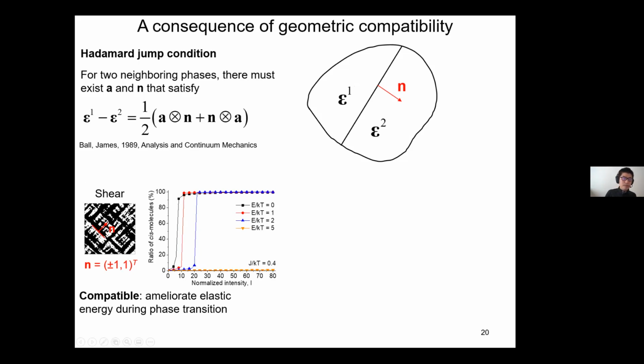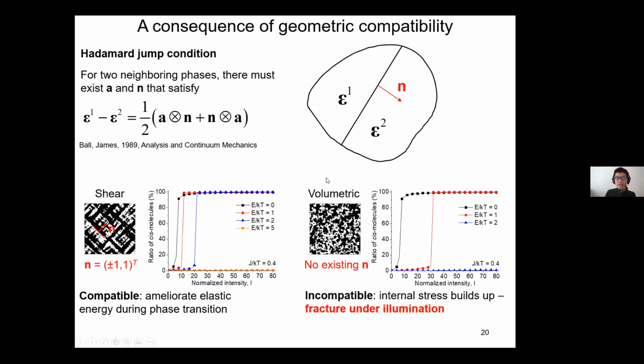You can actually find these vectors to satisfy this equation. So they can largely ameliorate or reduce the elastic energy you input during this phase transition. So this phase transition of material really involves very minimum elastic energy in this case, right? So it's easier. But if you have a volumetric photo strain,